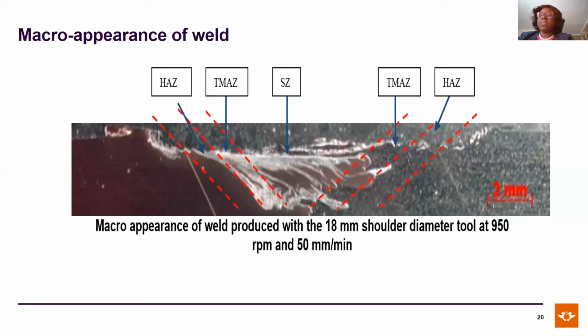So we then characterize friction stir welds into the stir zone, which is the center of the weld, where we plunge the tool. That is the point where the tool pin has acted during the weld. Further, from the stir zone, we have the thermomechanically affected zone, and then we have the heat affected zone. And then at the extreme, left and right, we have the parent material, as shown in this particular macro appearance. This will enable us to see the flow of the material that have been joined during the process.